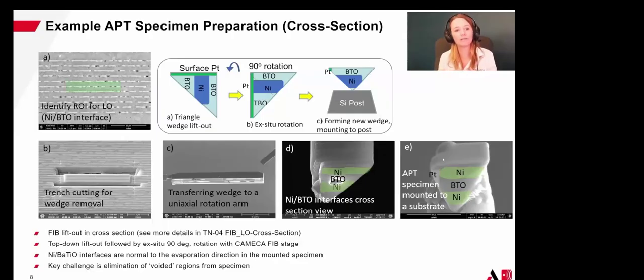Now, when we mill this with our annular mill process, we can adjust our final stopping point with our low kV milling so that we're end pointing the final tip shape so that it has that interface between our electrode and ceramic pretty close to the apex of that material. And that's going to give us a really high chance of success to collect that in an atom probe analysis.